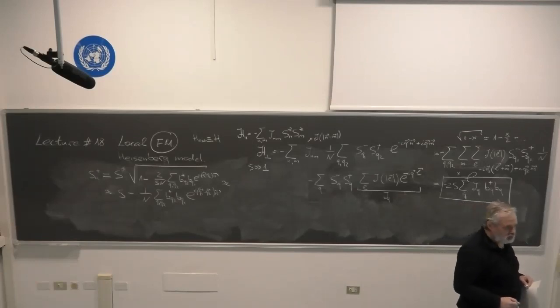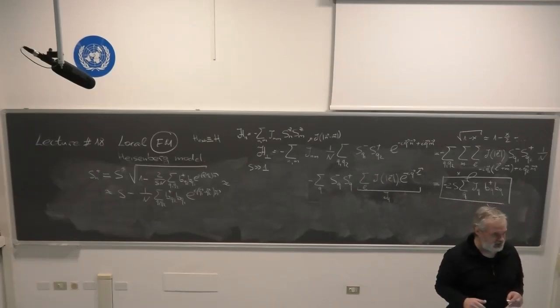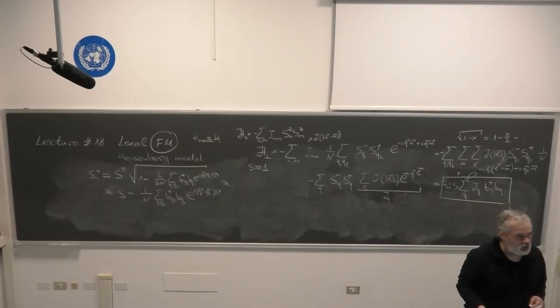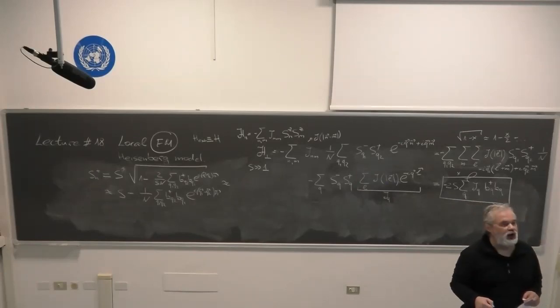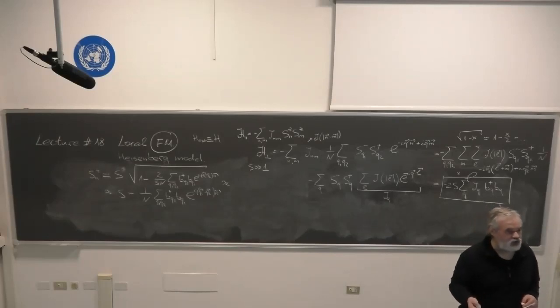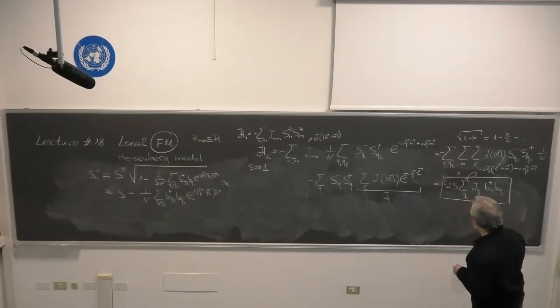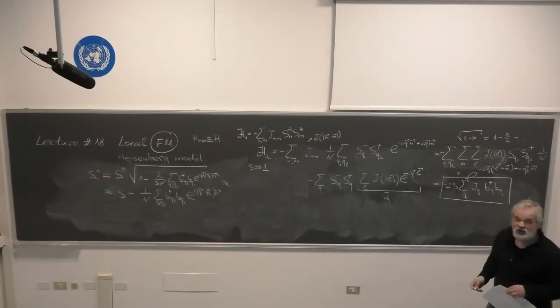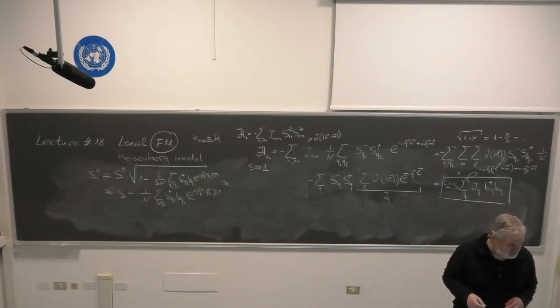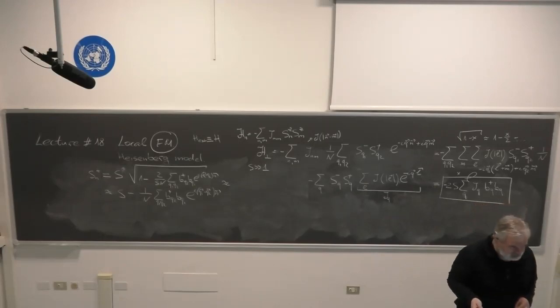In all these theories, what I'm presenting now is rigorously correct if spin is large or the coordination number, namely the number of nearest neighbors, is large. Then it's sort of a 1 over S or 1 over Z, inverse coordination number, expansion. However, it appears that this representation, because as I said this is sort of density of magnons, works well even for spin equal to 1/2. This is a big surprise, but rigorously, this expansion is not correct for spin equal to 1/2.